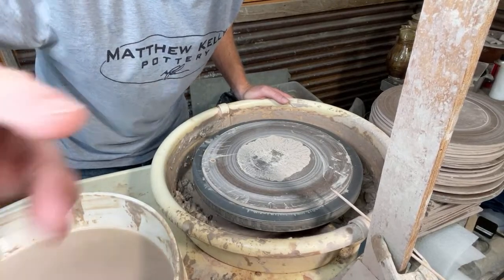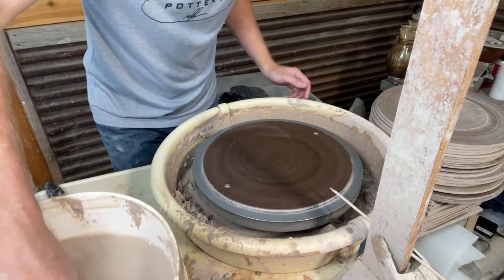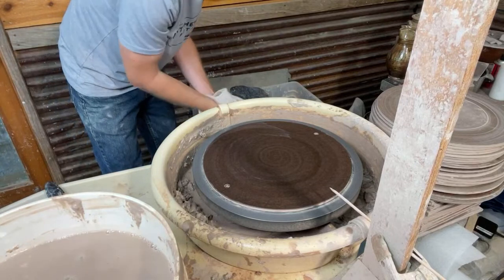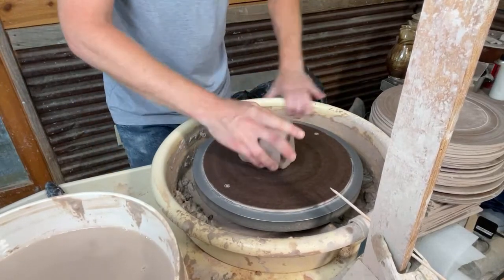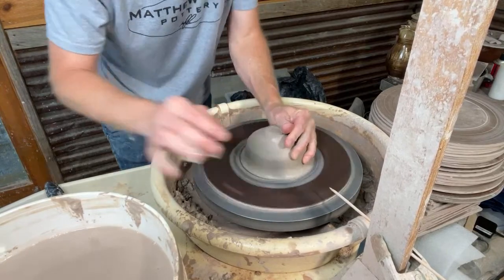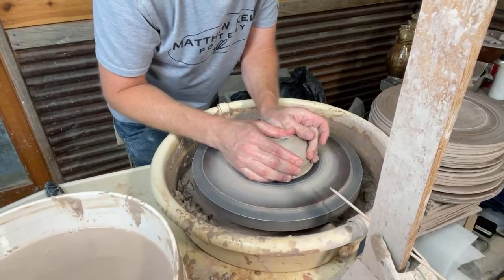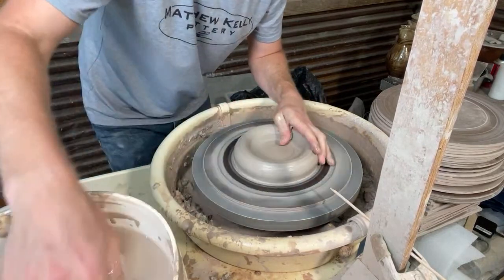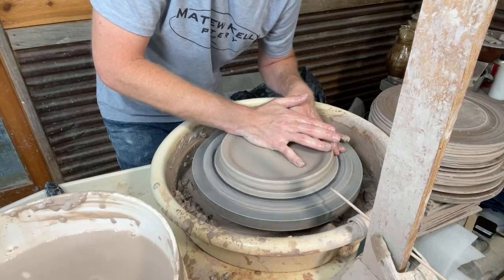Do I use the same clay body for everything? I use a different clay body for wood firing than for gas firing. I use a Hestia from High Water in my gas kiln, and I use a clay from Starworks, their Oka Medium, in my wood kiln. They're both high temperature clays, and I could probably use the Hestia in my wood kiln, and I've done a few pieces in it, but working with the Oka Medium in my gas kiln, I have had problems with some blisters in the glaze or pinholes, and it's mainly probably just a clay and glaze combination issue. I could probably adjust my firing to fix that, but haven't worked on it, and I have clays that are working in each. Since they're both high temperature clays, it doesn't really bother me to switch between them in my pug mill, and I just get a little bit of blending when I switch between the two.